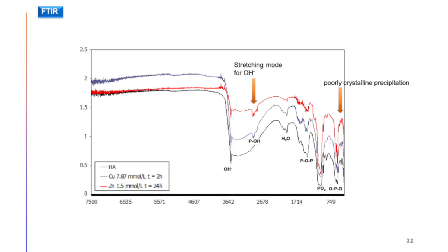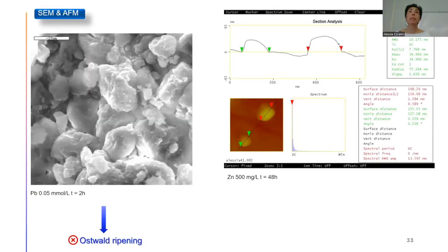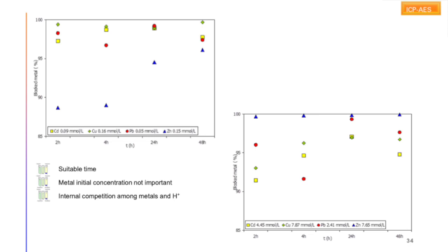So then we studied all the solid samples with the SEM EDS, and from EDS we can observe the presence of metals on the surface of the phosphate. With the SEM we can observe the shape of the particles. In particular, we can say that we didn't see the pyromorphite shape. Pyromorphite has a needle shape, but we observe a quite circular shape, and we also didn't observe a difference in the shape before and after the contact with the metals, so we didn't observe the Ostwald ripening phenomenon. Then we studied the solid samples with the atomic force microscope at Miami University, so we can better distinguish the shape of these particles and measure their dimensions to observe if there is a difference also with the dimension.